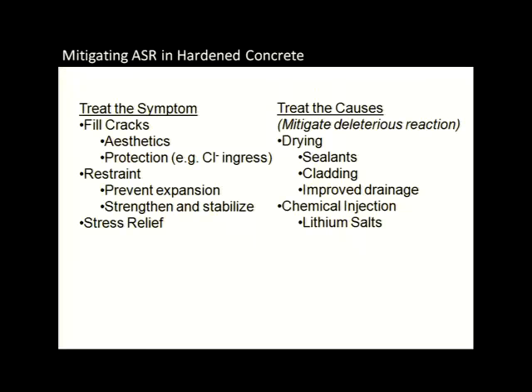So what happens if we have ASR actively going on in hardened concrete? There's kind of two approaches that we can use. We can either treat the symptoms or we can treat the causes. So you kind of see treating the symptoms on the left-hand side deals with filling cracks, trying to limit the amount of moisture that can come into the concrete. We can also provide external restraint, so carbon fiber reinforced polymers to provide the type of restraint around a bridge column that we would need to actually constrain the reaction from occurring, that outward expansion.